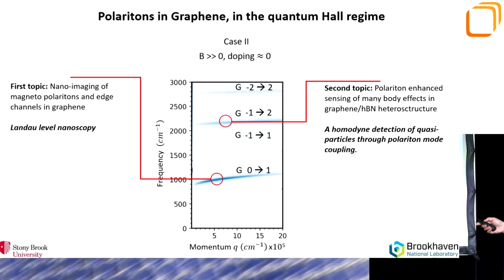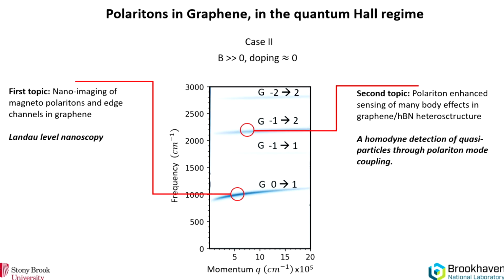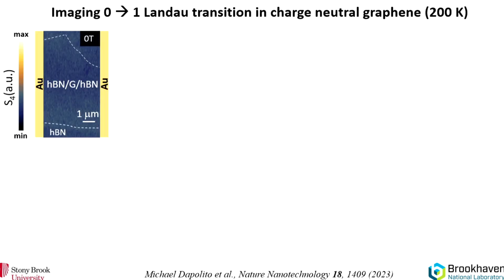So you can hybridize these Landau levels, which is highly tunable with magnetic field, with the phonon polariton modes at this frequency range, right? We can do this because we can freely tune our polariton frequencies, these magneto-polaritons, to match the phonon polaritons in hBN. Okay.